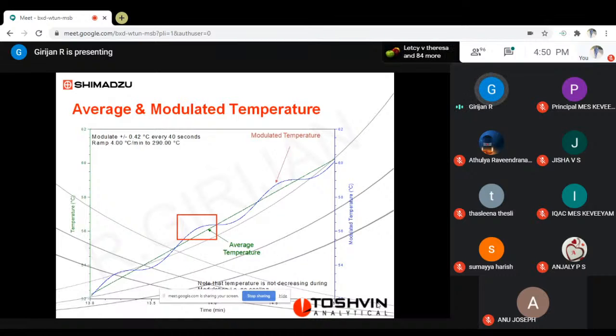In this particular experiment, we modulated plus or minus 0.42 degrees centigrade every 40 seconds. That means the normal ramping is 4 degrees centigrade per minute. We are starting from, say, 40 or 30 degrees, maybe room temperature, and going to 290 degrees centigrade, which is the maximum temperature. Our average, linear rate is 4 degrees centigrade per minute; that's our heating rate, our ramping rate. But every 40 seconds, we are changing this ramping by plus or minus 0.42. Either it will be 4 plus 0.42, and after 40 seconds, it will be 4 minus 0.42. So you have a modulation of plus or minus 0.42 over your normal rate of 4 degrees centigrade per minute.